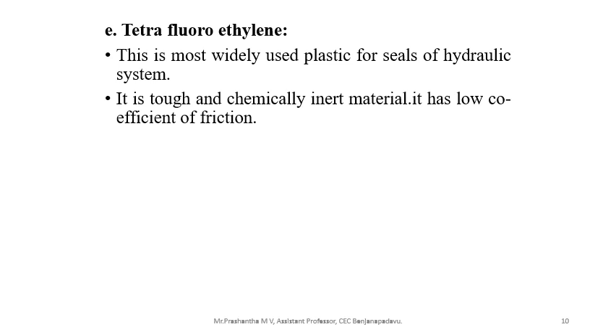Tetrafluoroethylene (PTFE): this is the most widely used plastic for seals in hydraulic systems. It is tough in nature, a chemically inert material, waxy solid, and has a low coefficient of friction. It has excellent resistance to chemical breakdown up to a temperature of 370°C, making it a very good material for elevated temperatures.